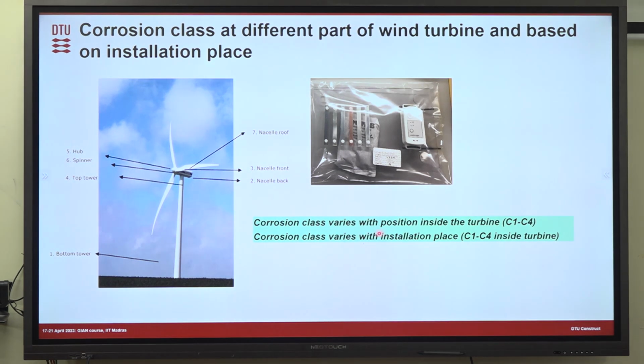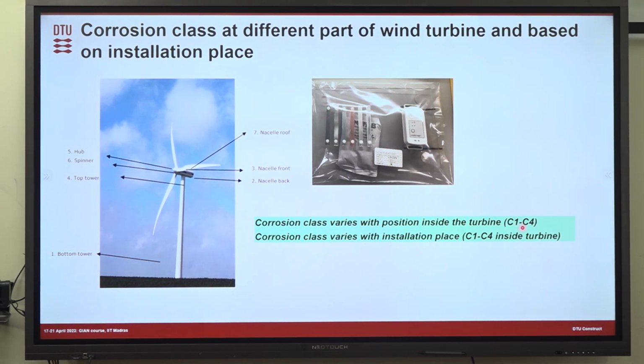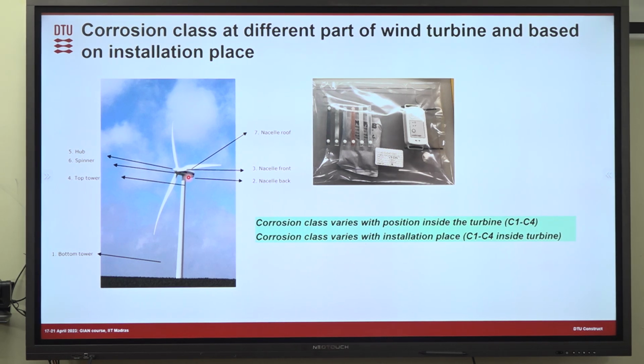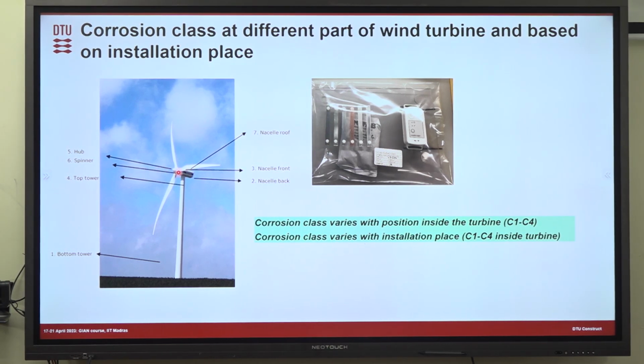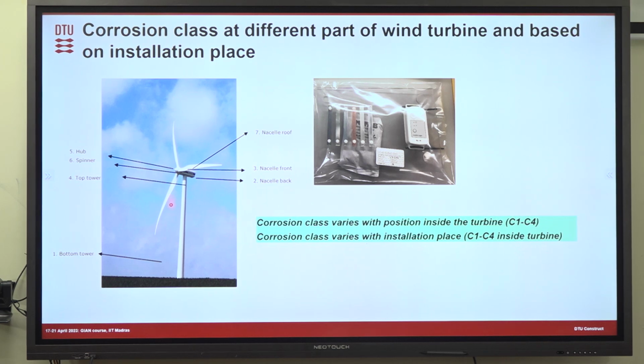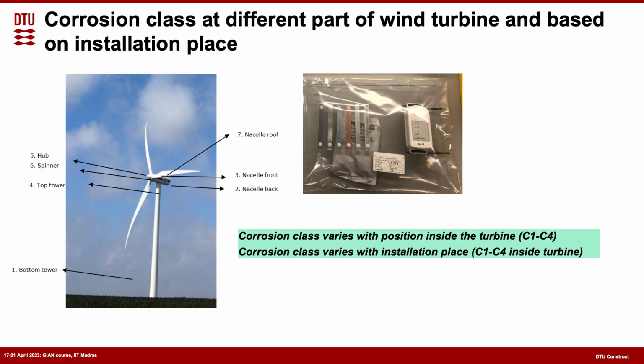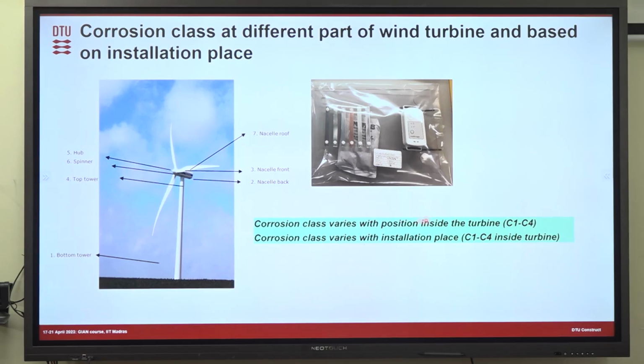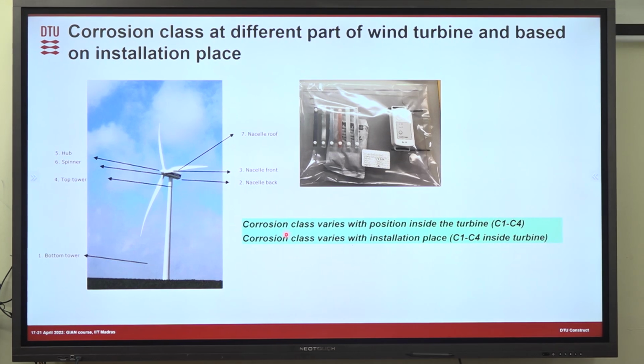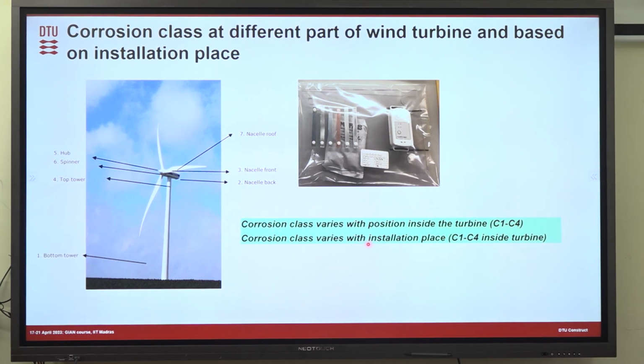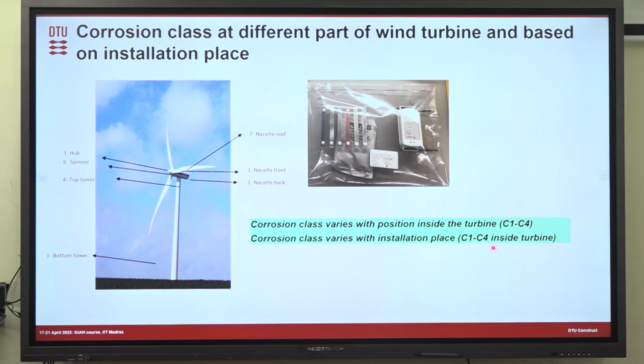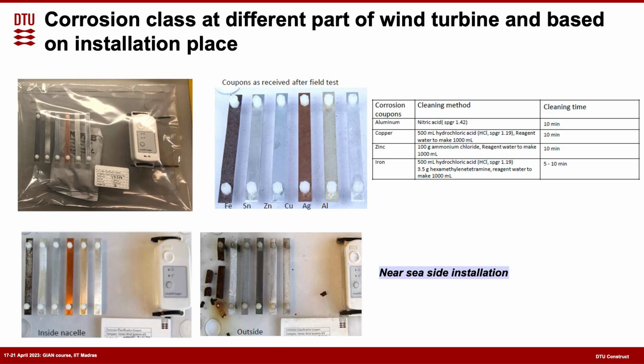Finally, we see that the corrosion class varies with the position inside the turbine, almost like C1 to C4. So you may get a C1 corrosion class in this part of the turbine, but there may be C4 here below. So all over the turbine, we didn't expect that as well, right? We know the corrosion class is different depending on the place in the turbine, and inside it can be much cleaner compared to below. So we see this C1 to C4, and I'll show you a little more detail on that. The corrosion class also varies with the installation place, almost like C1 to C4 inside the wind turbine. So after some time, we take out the coupons, for example.